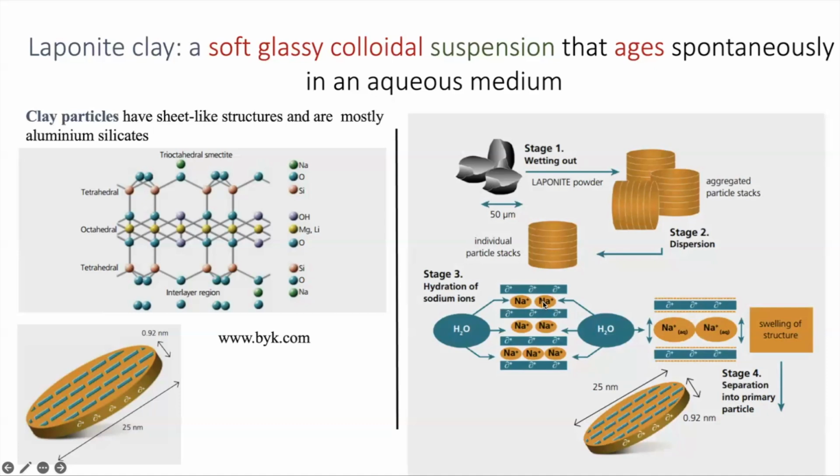So this results in swelling of the layer, and the sodium ions try to reach out into the bulk medium. So there is this swelling, and as the charge distributions continue to change in suspension, the clays in the tectoids, these one-dimensional stacks, continue to repel, because of screened electrostatic repulsion. And the moment the screened electrostatic repulsion exceeds the van der Waals interaction between the two particles in the tectoid, the clay stack starts breaking up. This process is called exfoliation.